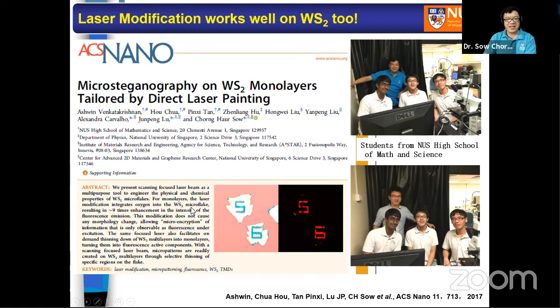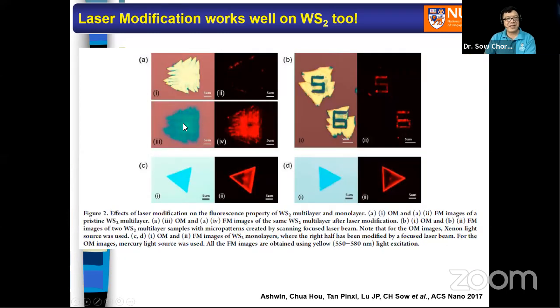Interestingly, they use a laser beam to modify the WS2. The original pristine WS2, this is multiple layer, doesn't show promising fluorescence. Laser beam modified gives you very bright fluorescence. And you can use a laser beam to write the number 5 and then the 5 becomes fluorescent. And the bottom rows are monolayer.